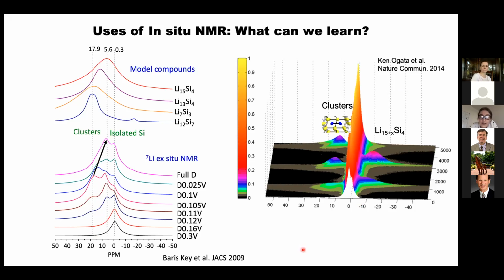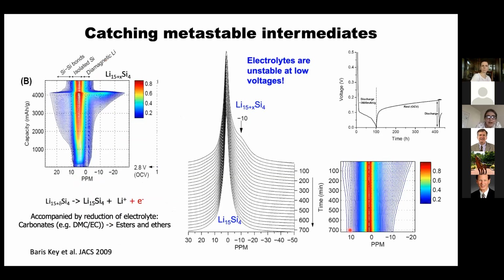We did it originally in this JACS paper, but this is another series of work where we did it on silicon nanowires, where you can see beautifully that you form these clusters. But what's surprising is you see this peak at negative ppm, which is the so-called Li15+x phase, where you've added a little bit of extra lithium to this Li15 phase, and you can see you've dramatically shifted the frequency. And this is again just showing the same thing now as a contour plot, so here's the Li15 phase.